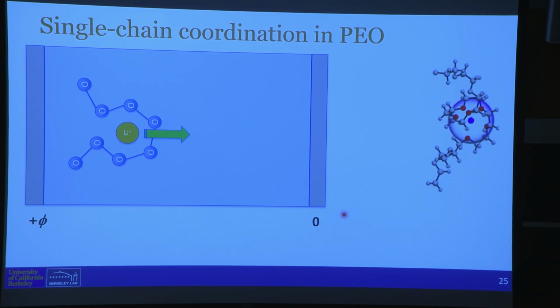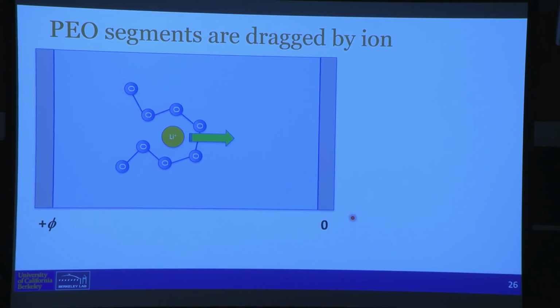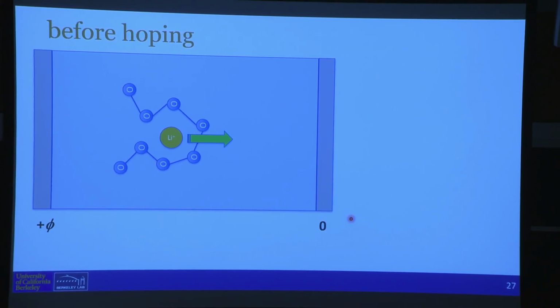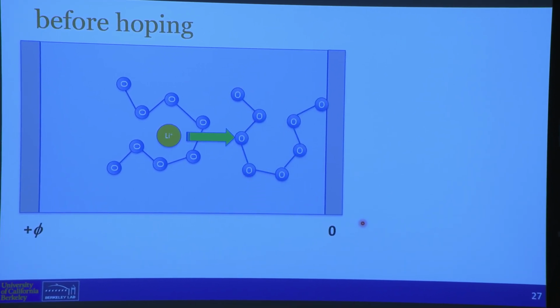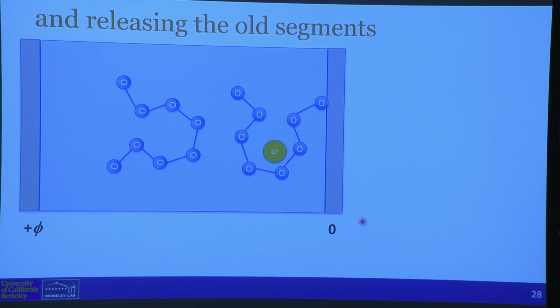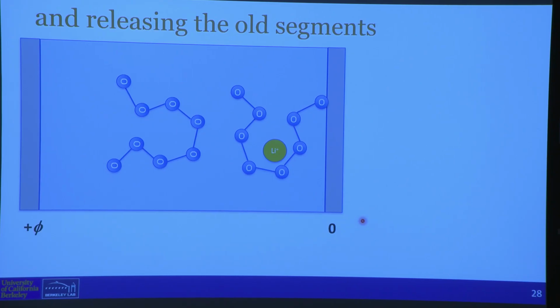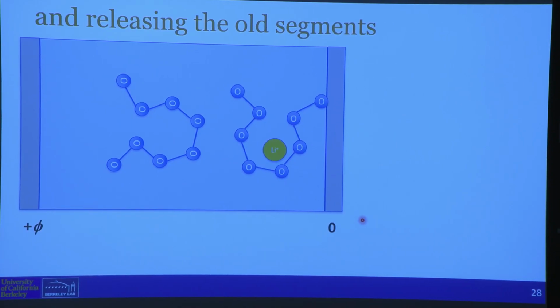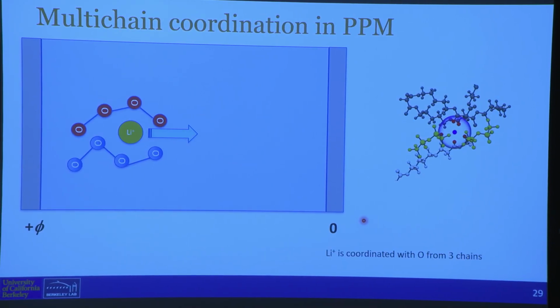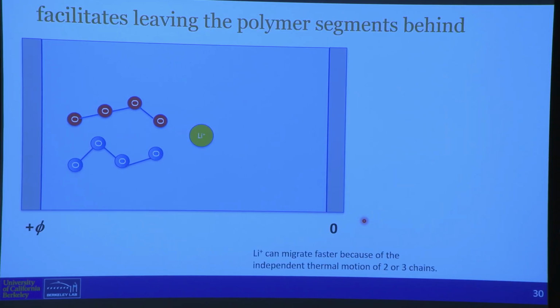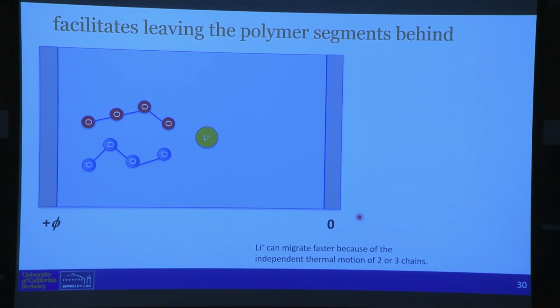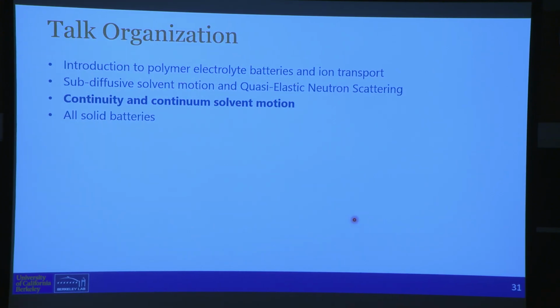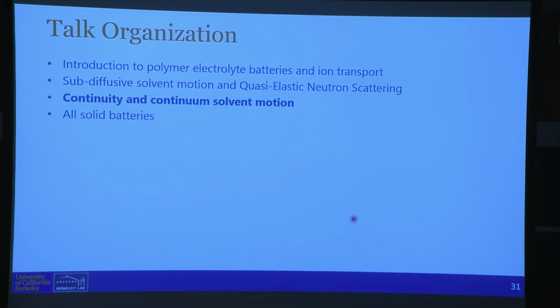As the lithium ion is heading towards the negative electrode, it carries too much of the uncharged species, and then at some point it decides to hop. Most of the literature on polymer electrolytes has been focused on this hopping, not the dragging. But the dragging is more important than the hopping, in my view. When you have 2 chains, you don't have the same constraints, and it leaves the polymer chain behind more efficiently. That's a molecular hypothesis. I have not shown you any data on transport, which I will do next.